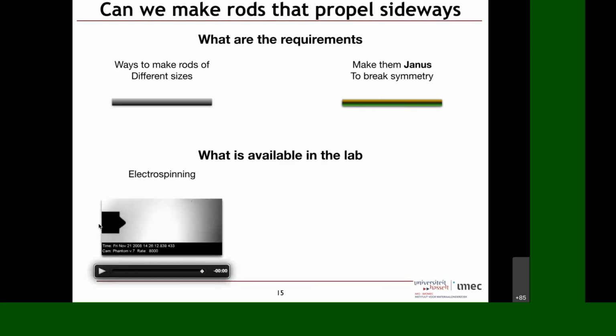So I was already working on electrospinning to make fibers. I thought, oh, maybe I can use the fibers to make it. So you make electrospinning. The easiest way is you push the solution here, you put a very high electric field, the droplet gets pulled, which has polymers in it. While it's going, it evaporates. Mostly we use ethanol or dichloromethane. They evaporate very, very fast into the atmosphere. By the time this jet comes here, all solvents are evaporated and you only get polymer fibers here. So this is one method to make this thing.